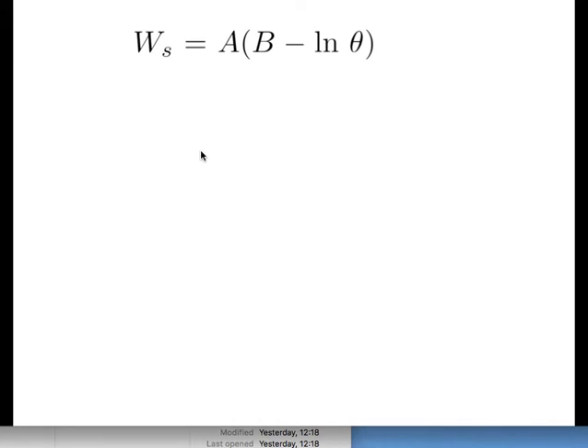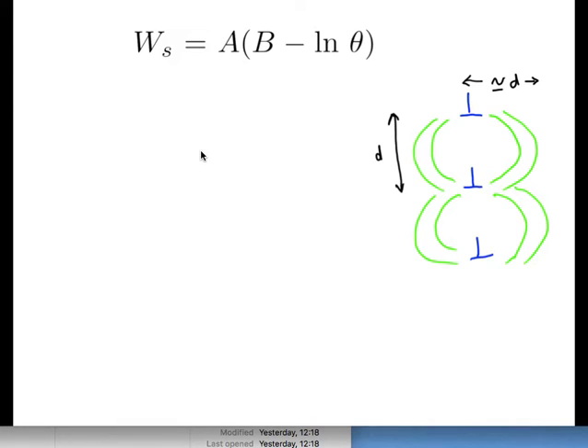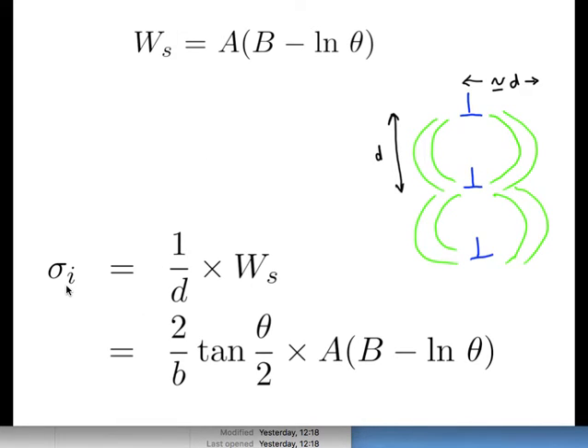And starting with that equation of energy per unit length, the interfacial energy per unit area will be 1 upon d, that means the number of dislocations in a unit length of interface normal to the dislocation line, times the energy per unit length of the dislocation. And we now have an equation which tells us the interfacial energy per unit area of that tilt boundary that we started off with.